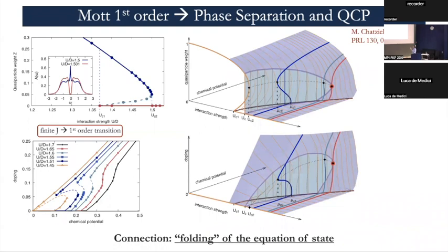This can be seen because of how we have connected this adiabatic continuity and the folding of the equation of state here at half filling with the same phenomenology that we have out of half filling, and it can actually be seen in a three-dimensional way, if you like, as a generic folding of the equation of state. For instance, this curve is the Z and here the doping, plotted on the same space of thermodynamic parameters, which are interaction strength and chemical potential. This folding of the equation of state that you can see in this quantity and in this other quantity is really the outcome of this curve, which is exactly this one. And if you cut instead in chemical potential, you will have this kind of curves, which are these.